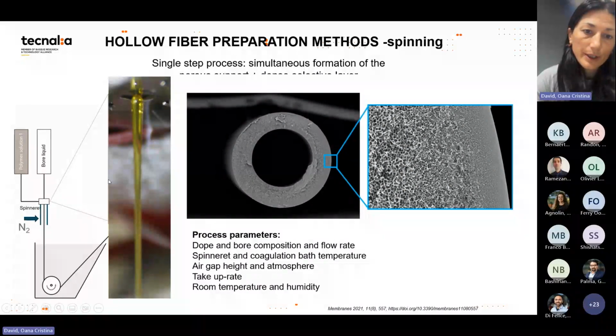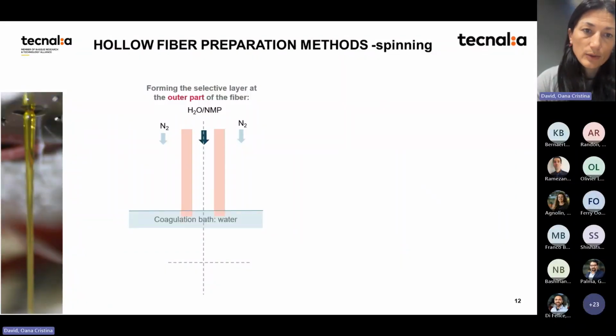Yes, so we have many process parameters that we need to control and optimize in order to achieve this nice structure we have here as an example in the picture. And sometimes we can place nitrogen outside to promote solvent evaporation on the outside in the air gap to achieve this densification of the polymer before coagulation in the water bath, where the porous substructure is formed. So this is the classical way for gas separation membranes. As I said, we have a nitrogen stream outside, inert gas, and for the bore liquid, we have water mixed with NMP. So then we form the selective layer outside.